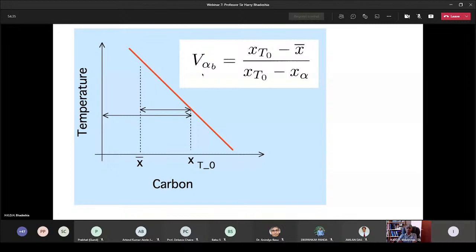So it seems that we are stuck, okay? This concentration is almost zero, so you could ignore it for the moment. Normally when I'm giving a lecture, I ask the students, just looking at this equation, is there anything we can do to increase the volume fraction of bainite? And there are three answers. Obviously I can't interact with the audience today, but if you decrease the average carbon concentration, then this will increase. And we don't compromise the strength, because the strength comes from the very fine bainite plate. So decreasing X bar would do it.